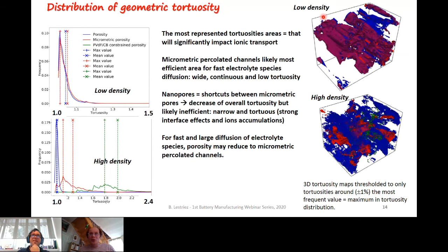And you can see that in a low density electrode, the area for total porosity and the micrometric porosity are similar, but in a high density electrode, the area in blue, which corresponds to the most represented tortuosity value for the total porosity, is covering a much wider area than the one for the micrometric porosity. This simply underlines the fact that between the micrometric channels in high density electrode, you have nanopores that are forming shortcuts and that are connecting all these micropores.